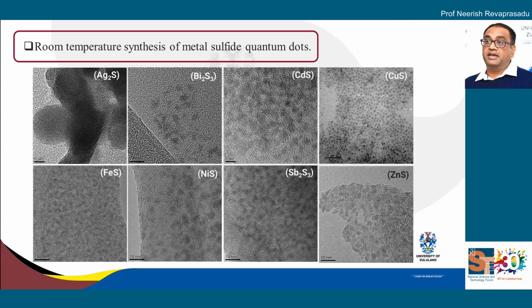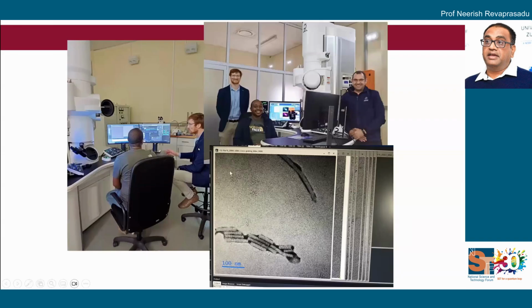We've made room temperature metal sulfide quantum dots, and this is a whole range. So we can make almost anything that we want. These are silver sulfide, bismuth sulfide, cadmium sulfide. We are focusing on cadmium sulfide and selenide at present, but we can make a whole range of quantum dots. So this is our microscope, the JEOL F200, and it gives us good resolution. You can see some of the figures that I showed you. It's almost atomic size resolution.